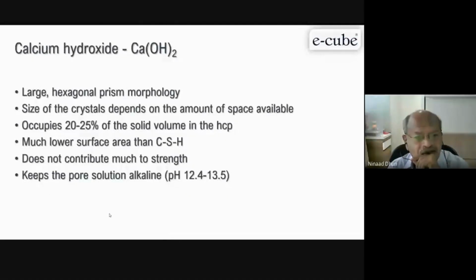Now, you can see the morphology of this, how the shape of the crystals is, the space available. Calcium hydroxide occupies 22 percent of the solid volume in hydrated cement paste. It does not contribute strength, but keeps the pore solution alkaline. Now the alkalinity of the cement paste or concrete has to be maintained within this range, which also protects your steel. So with time, when it is carbonated, it is reduced to 9, 10 like that. Then it starts reducing its durability. So cement is always an alkaline material. That's why if you add acid, you'll see it dissolving.